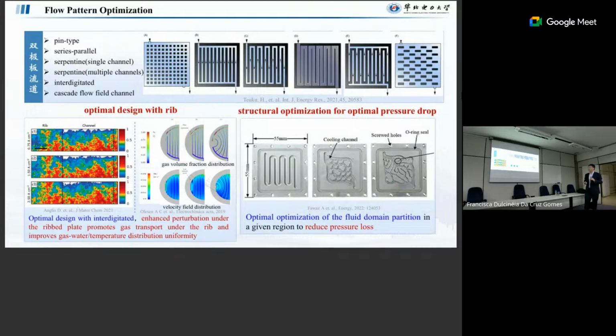Yeah, these are also people working. Basically, this design came from fuel cells, but nowadays they try to use it for water electrolyzers, and it works. I think they don't have something special, but for me the most interesting part is this one, interdigitated, because normally for different layers, the transport is all by diffusion. Due to temperature, they will have a little bit of convection, but not serious. But if we use interdigitated systems, that means they block the way the water has to go down and go up. That means we change the diffusion to a pressure-driven system.